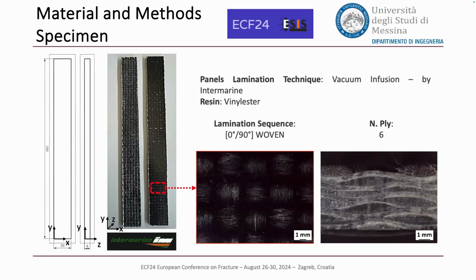About the specimen, the panels were made by vacuum infusion by Intermarine Messina. The resin is vinyl ester. From these panels, we extracted rectangular specimens that you can see in the photo. In the microscopic image, you can see the lamination sequence that is 0/90 type woven, and the number of plies is 6.